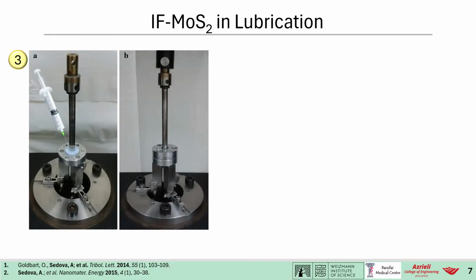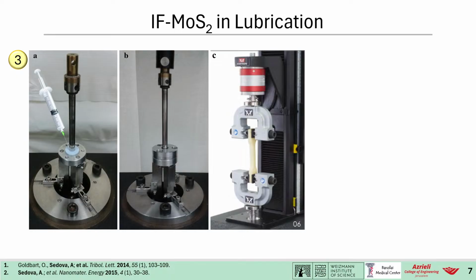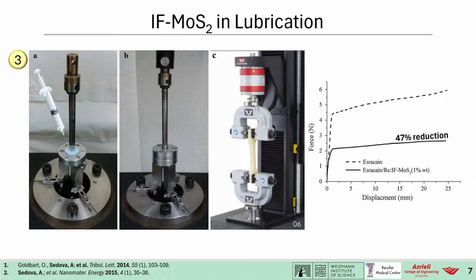And then how we were testing, basically. We designed a device that could fit into an engineering machine. It's called an Instron. This machine is used to test the resistance of materials to tension. Basically, there are two parts. One goes down, one goes up, and there is a load cell measuring the force. And we designed this device to fit exactly into this machine. What we were measuring is the force needed to extract the device we are testing from these soft rings that we designed. And we saw a reduction of about 47% in the force needed to extract the device.